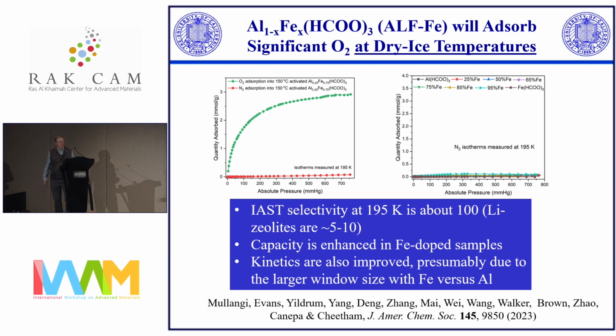So this is not the most versatile of MOFs. One of the things that Mohammed's shown is how you can fine-tune things with all his design strategies. There's not a heck of a lot that you can do with ALF, but one of the things you can do is substitute other metals, such as iron. When you dope iron into the ALF, iron's a bit bigger than aluminum, and it expands the window and the cavity a little bit. So it improves both the kinetics and the capacity for absorbing oxygen. That story is a little bit more complex than I've told it, but to a good approximation, that's how this works.